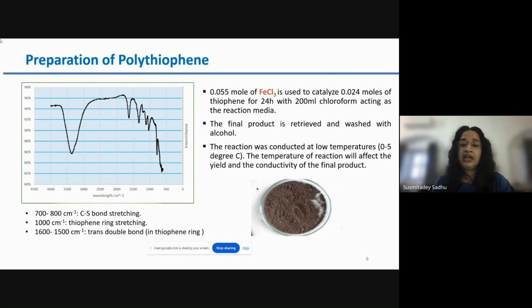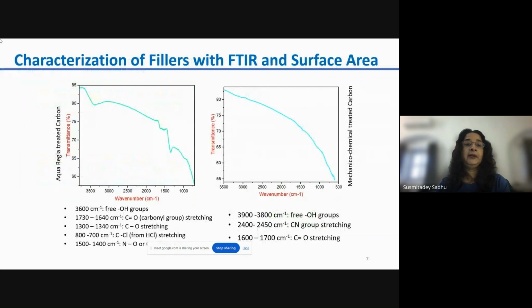So the polythiophene that we prepared in the lab was characterized by FTIR, and there we can see that it has the presence of C-S bond stretching, thiophene ring stretching, and trans double bond present in thiophene. So that confirms the preparation of polythiophene in the sample.